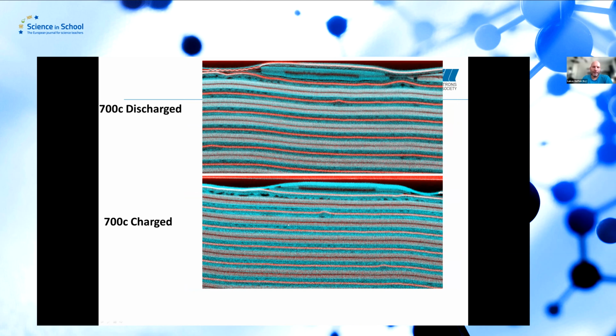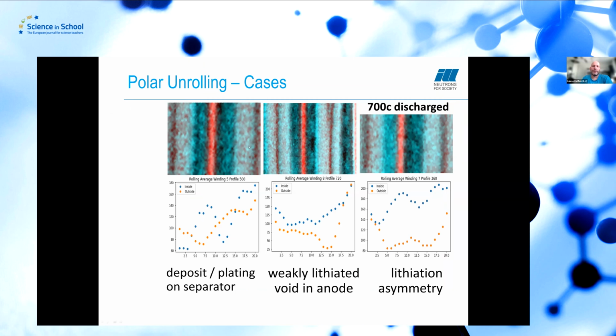So that we can then look at the different cases that we can see. We have here, for instance, voids that appear in the anode material. We have plating of the separator materials, for instance, here between the anode and the cathode that can occur. Or we can see asymmetries between the inside and the outside anode, because it's a sandwich structure, where you have an anode material on both sides of the copper current collector.